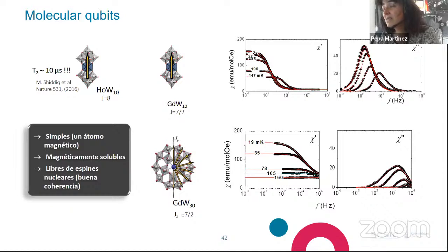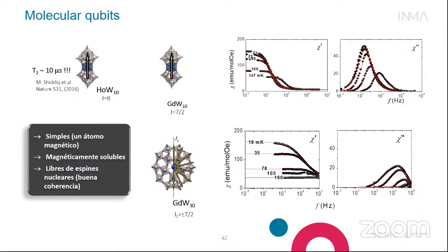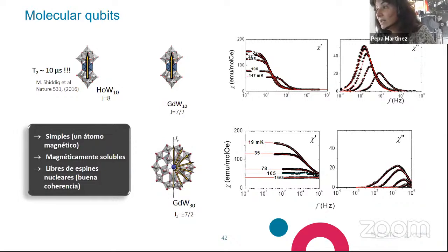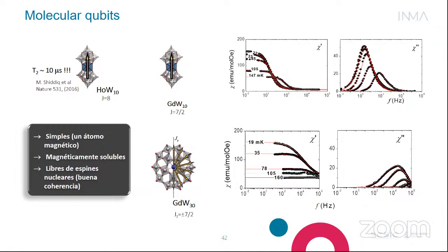One possibility is that, something we observe is that once the system is ordered by means of dipolar interaction, this mechanism dies out. So somehow the dipolar interactions do play a role here. So what we believe is that this energy is dissipated to the bath through some kind of dissipation with, of course, phonons, because they feel the temperature of the bath. If you would have a temperature sensor nearby, you might be able to measure the increase in temperature.